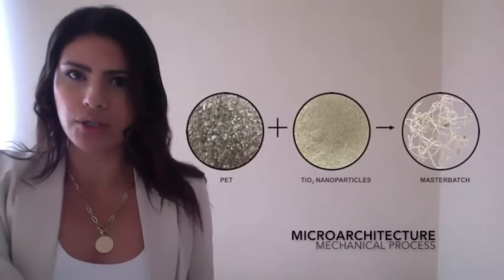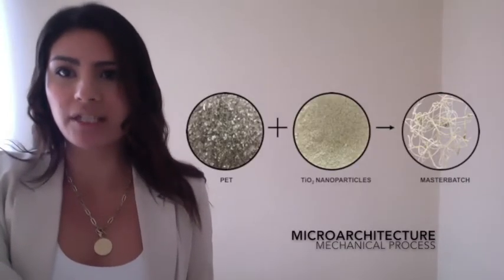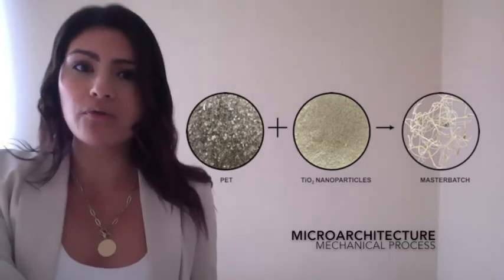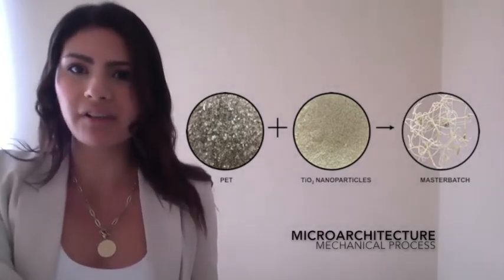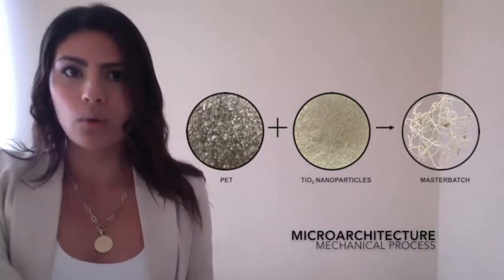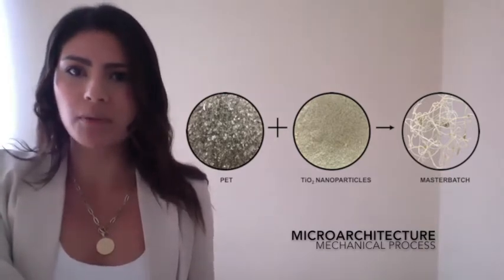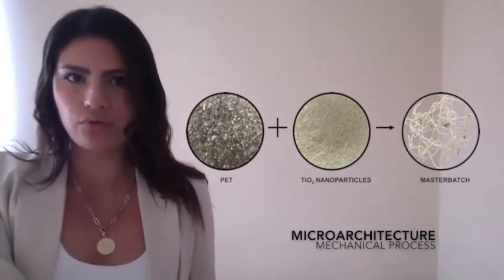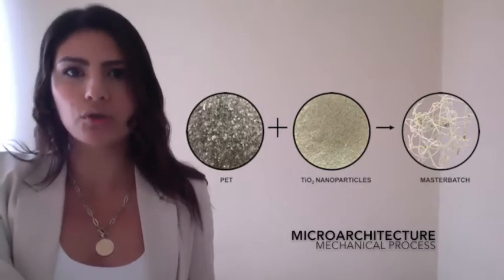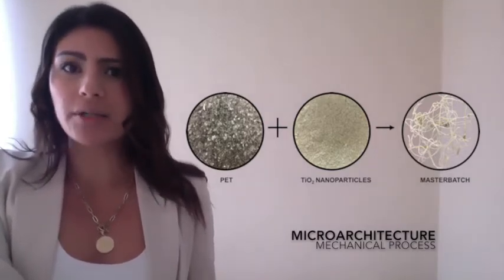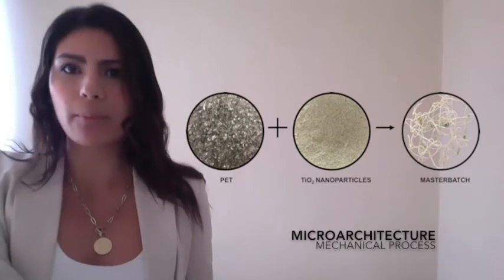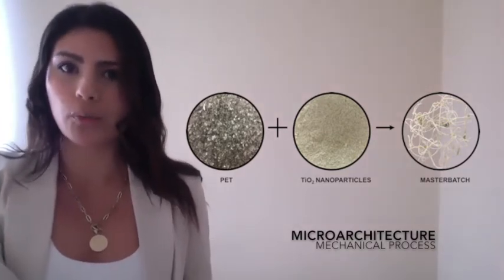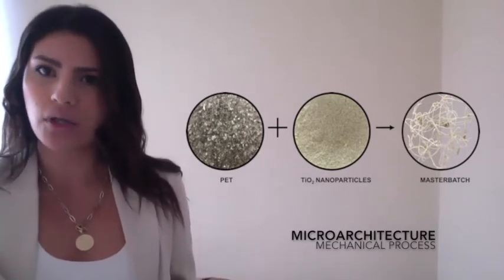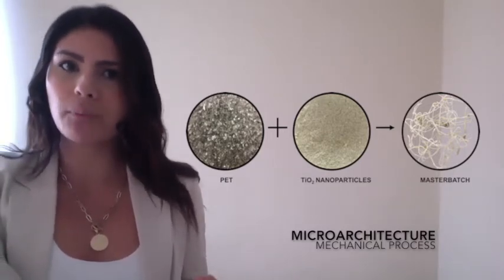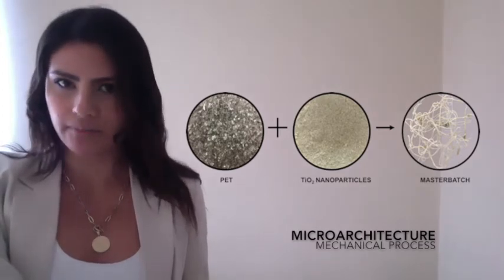Component proportions and a number of variables relating to the mixing process itself were found to be crucial to ensuring the stability of the new material. We succeeded in establishing the optimum temperature and mixing duration for thermofusion and extrusion of the components. A larger proportion of nanoparticles results in a more fragile master batch with reduced elasticity, while the incorporation of too few nanoparticles will diminish the photocatalytic properties of the material surface.